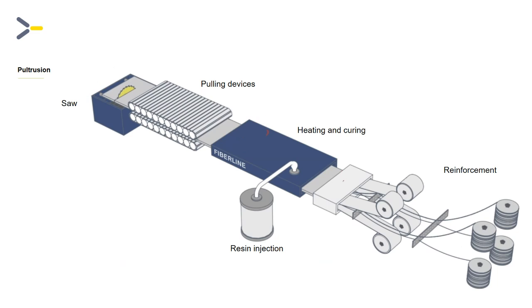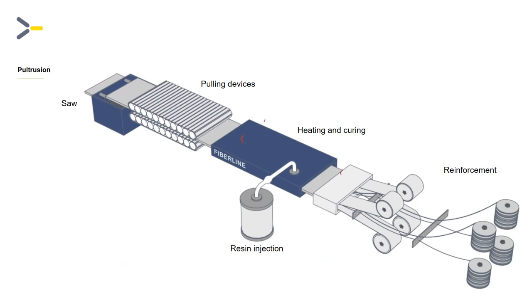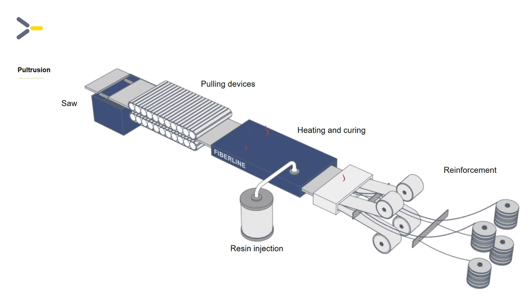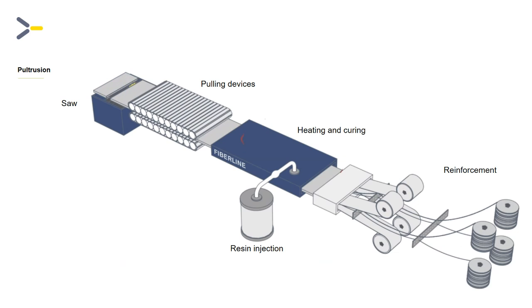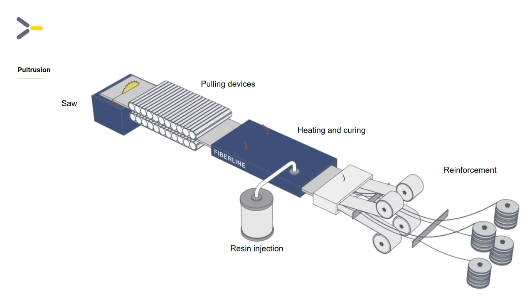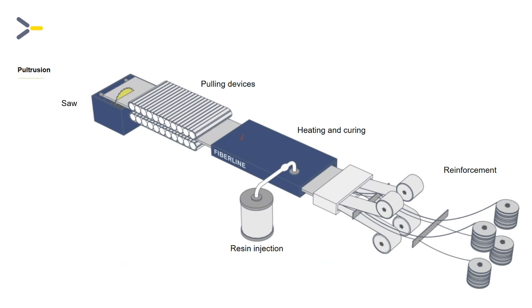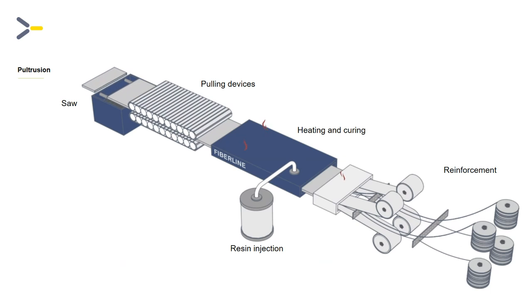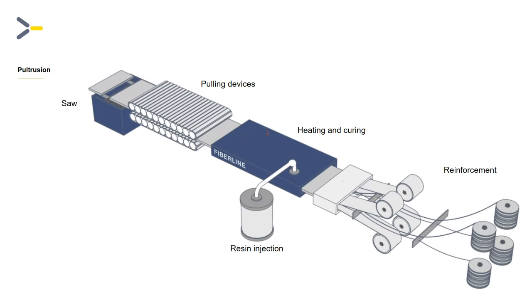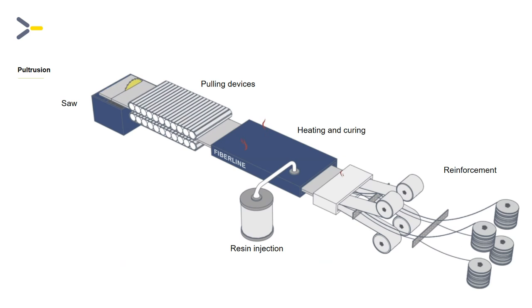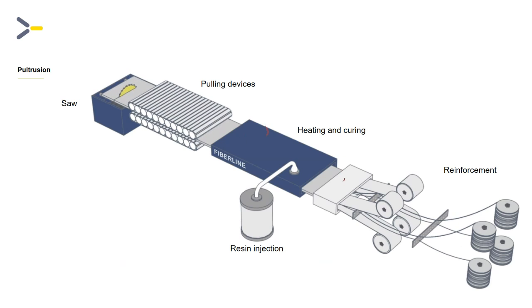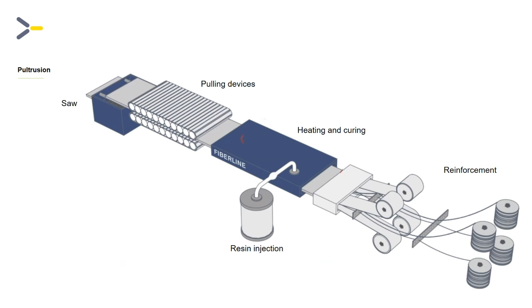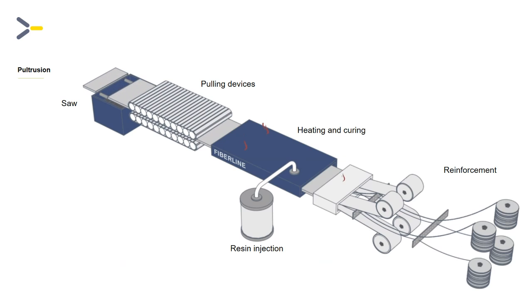This is the process, more or less. On the right, we have our dry ingredients as our reinforcement by means of unidirectional fibers and mats. They are pulled through a preheater, where the fibers are preheated to about 50 to 60 degrees Celsius, removing the last moisture that may be in the reinforcement. Then they are pulled through heating and curing tooling, and this tooling is normally made of stainless steel, of steel with chrome surface coating on the inside. This tooling is about 1.5 meters in length.